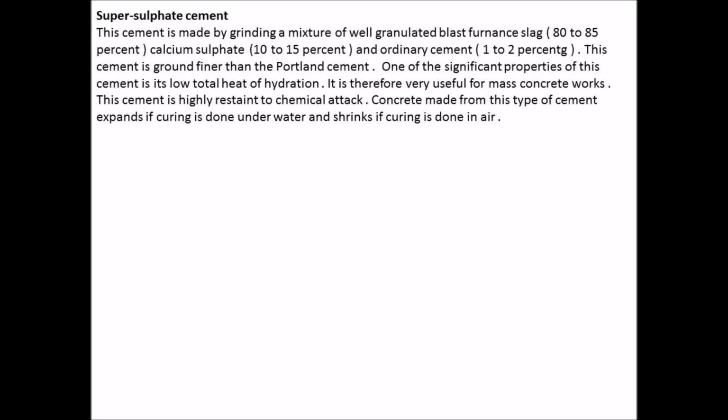But it's expensive. Concrete made from this type of cement expands if curing is done underwater and shrinks if curing is done in air. It's a very important point, guys. If you're using this kind of cement underwater, like piles of bridges, it will expand, okay?